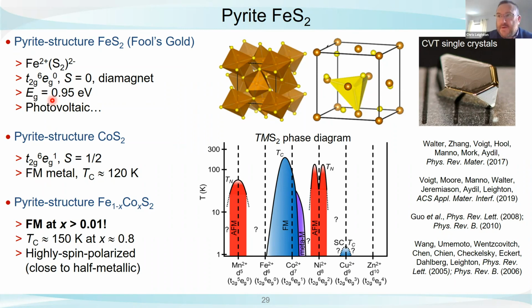Okay. Now, if you go one element over in the transition metal disulfides, this is the global phase diagram. If you go from iron disulfide to cobalt disulfide, then you add 1 electron in this eg sublevel that produces spin of a half. It becomes a ferromagnetic metal. It has a TC of about 120 Kelvin. Now, what's really incredible about this is if you make alloys between iron disulfide and cobalt disulfide, putting in as little as 1% cobalt disulfide induces ferromagnetism, and the TC of that ferromagnetism races up. It becomes about 150, 160 Kelvin eventually. So you have diamagnetism in iron disulfide, but it lives very close to a ferromagnetic ground state, and it led us to wondering, without adding magnetic cobalt dopants, but just by adding electrons on the surface using our technique, could we ever induce ferromagnetism in this material from a spin 0 starting point?